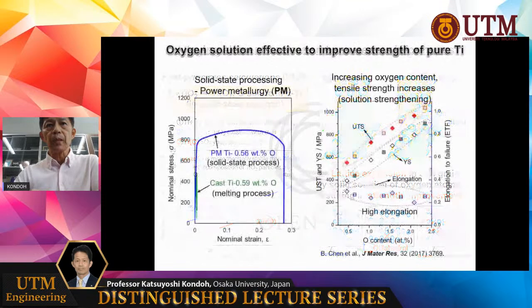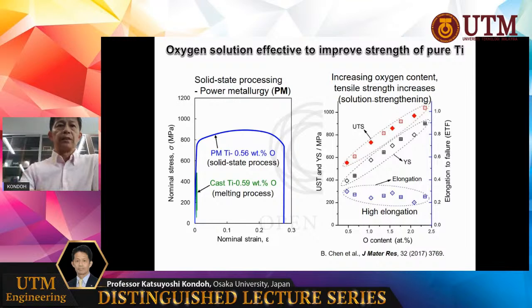But anyway, based on these results, we prepared titanium with about 0.6% oxygen atoms included by the powder metallurgy process, PM process, in solid state. Compared to the cast materials, we can see in the stress strain curves that the powder metallurgy material shows very high strengths and very good strain, good ductilities compared to cast materials.